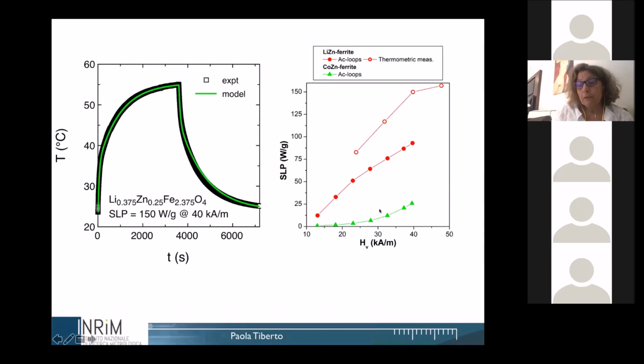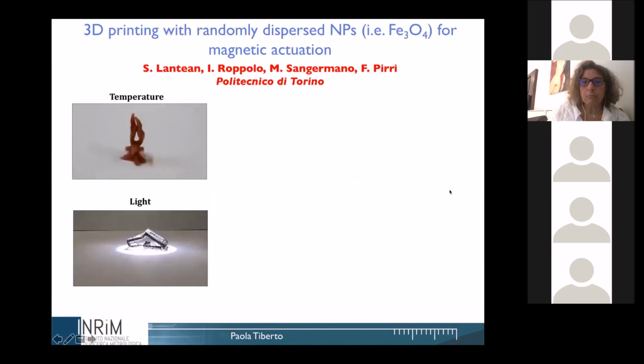These are the SLP. This is interesting because it is the specific loss power measured or calculated by the three techniques: we have the AC loop, the thermometric measurements, and the static hysteresis, of these lithium zinc ferrites. These are the ones measured with the thermometric technique in the hyperthermia setup, while these are the contribution measured with the conventional hysteresis that I've shown you before. You can see that the thermometric measurements possibly take into account also other kinds of thermal losses. I think that I've exceeded my time.